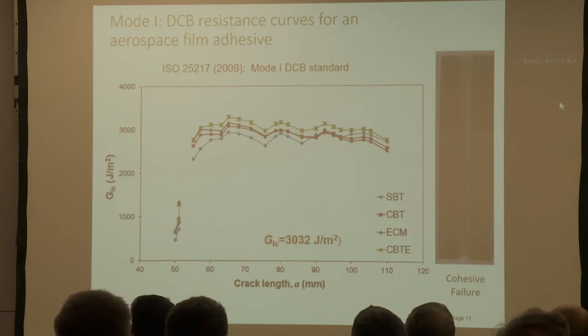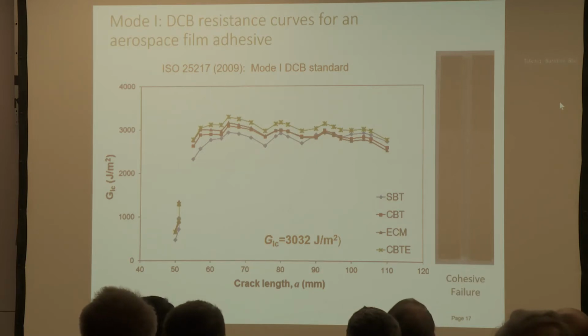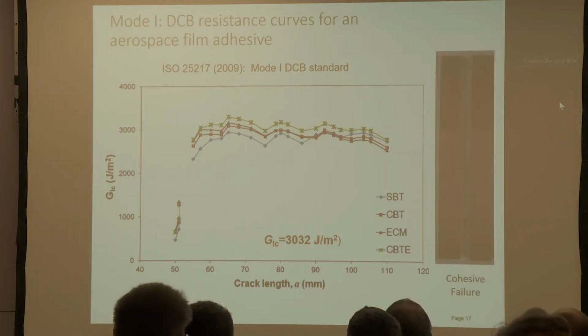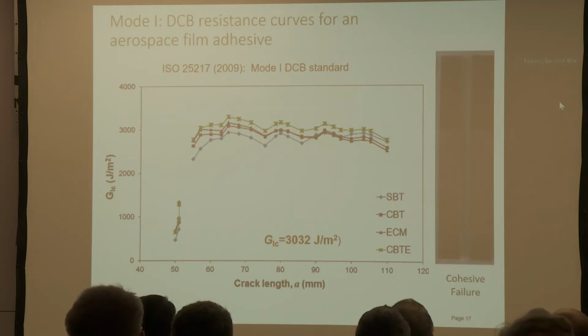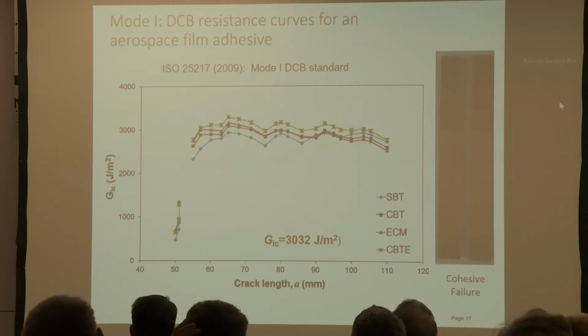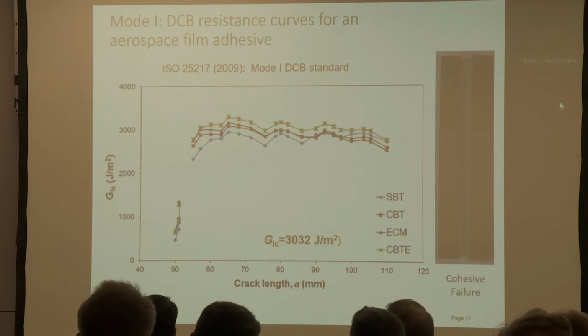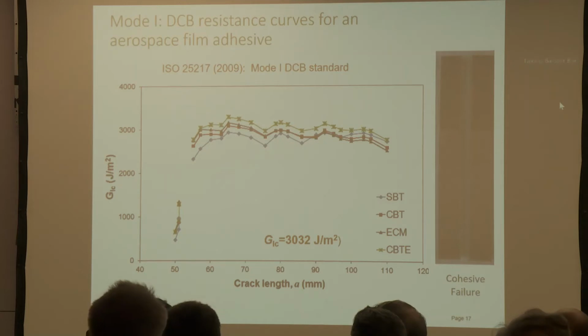And one thing that we wanted to explore additionally was the use of an effective crack length approach. So in addition to the three methods for reducing the data, there is the corrected beam theory with effective crack length, CBTE, and the idea of that is that the use of effective crack lengths can negate the need to measure crack length. So there are situations, a little bit like with the tapered double cantilever beam, where you can negate the need to measure crack length, if you're using effective crack length approaches. And various groups have implemented different versions of the CBTE method. I'll return to those in a little while because obviously they can also be used in mode 2.